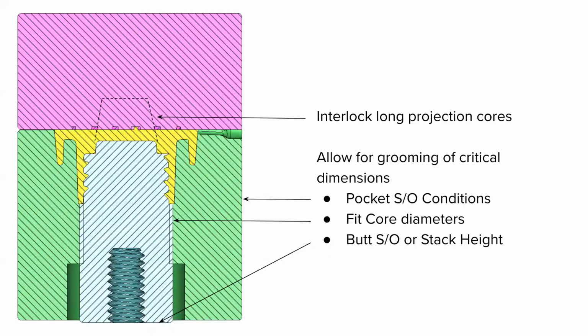Likewise, one of the things that we do is we allow for grooming of critical dimensions. Now, if you notice Jake's mold, his was done in an entire printed cavity. The gate came in on center. The melt never had to cross a transition. Ours is put inside of a nest inside of a metallic mold set. So anywhere that our flow is crossing over that seam line, you have the potential for flash. Therefore, our part outsides are groomed to fit the pocket, so we're not flashing down in between.